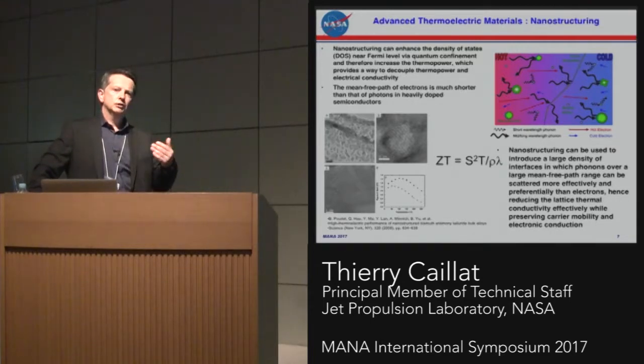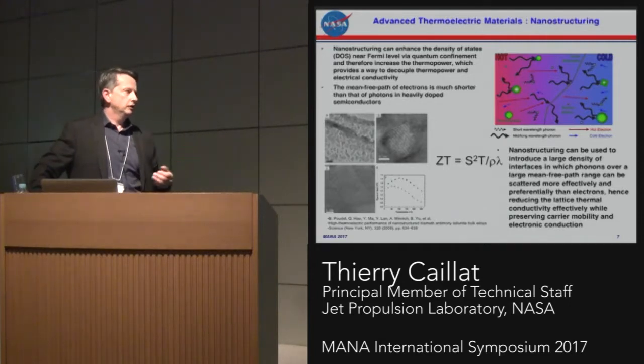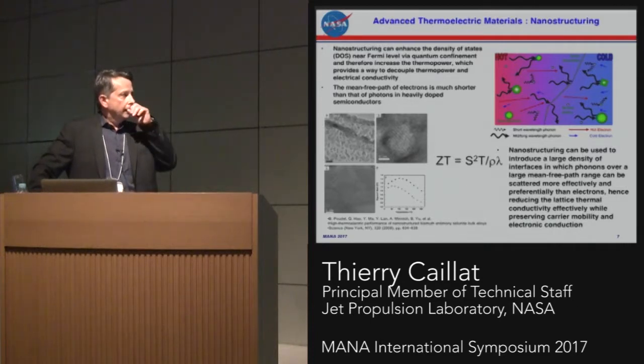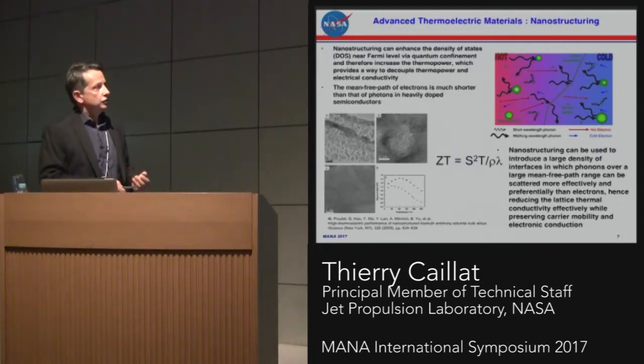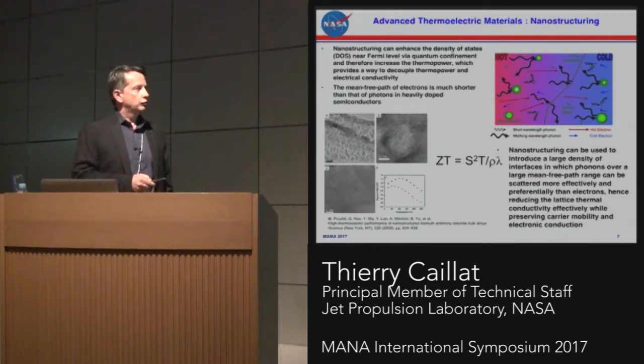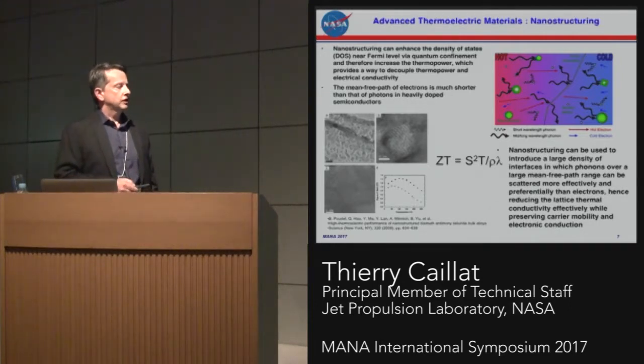And there are two ways that you can potentially use this to your advantage. One is manipulating the density of states by doing energy filtering and quantum confinement. And by putting all the states near the Fermi level, you can potentially increase the Seebeck coefficient. The other way is to reduce the thermal conductivity by putting a number of interfaces in the materials, therefore scattering, hopefully preferentially, the phonons versus the electrons that tend to have a larger mean free path. And therefore, overall, you get an increase in the ZT.